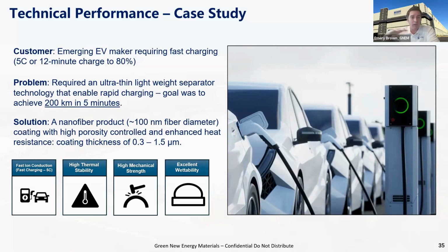So they could be coated, dispersed coating onto the membrane, onto the base film, if you will. And this ultimately allowed for enhanced heat resistance, but also allowed for the high porosity that the customer needs for fast charging. When this first came up, it was a big breakthrough for the company to offer this nanofiber coating. And today it's one of our premier products.